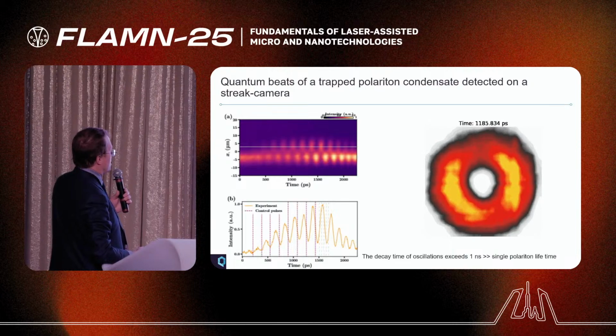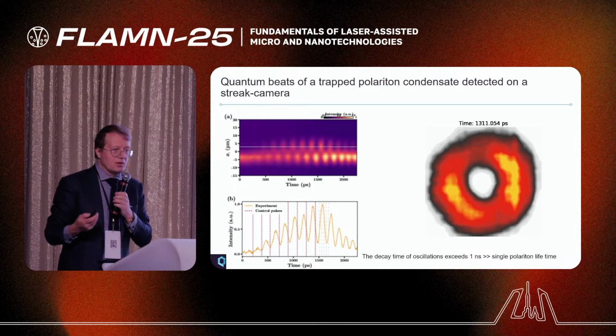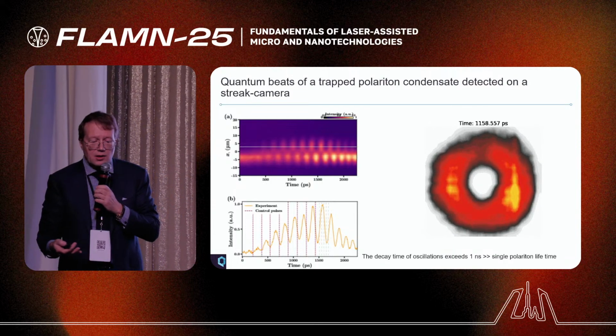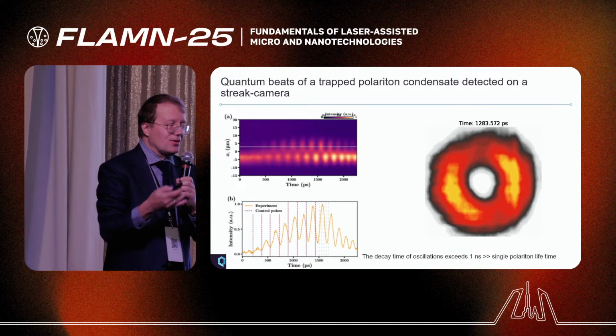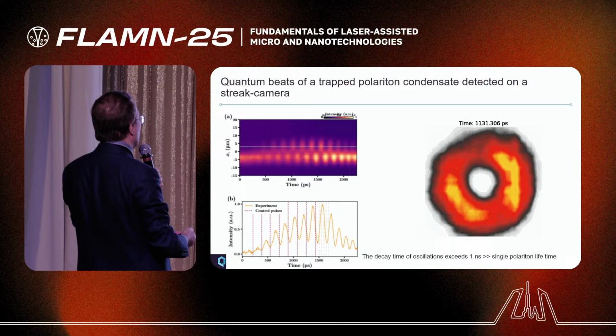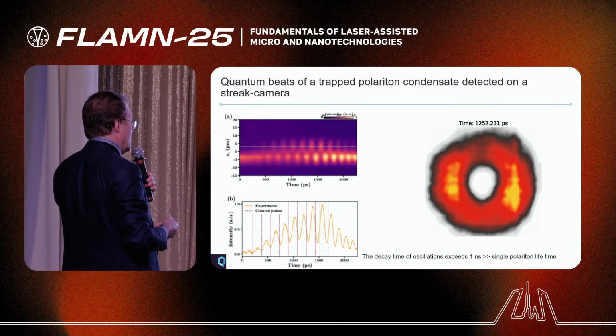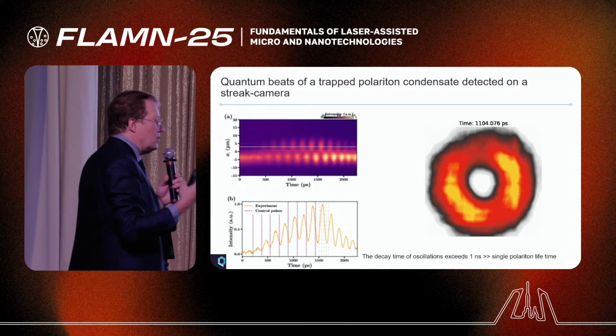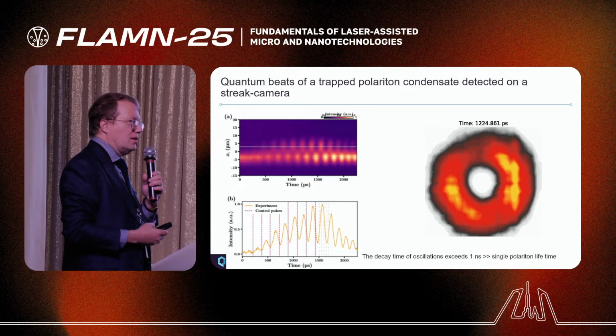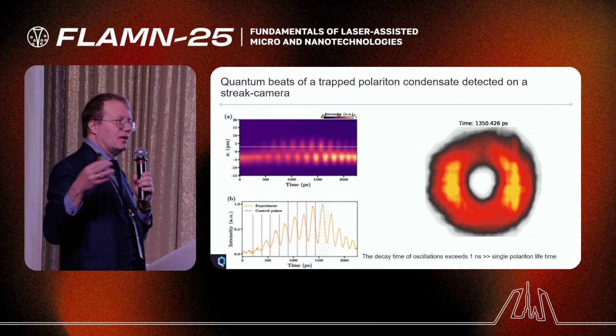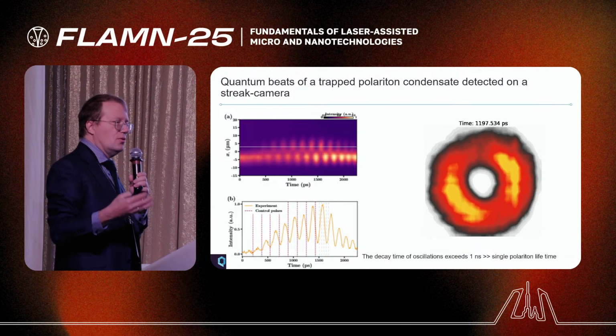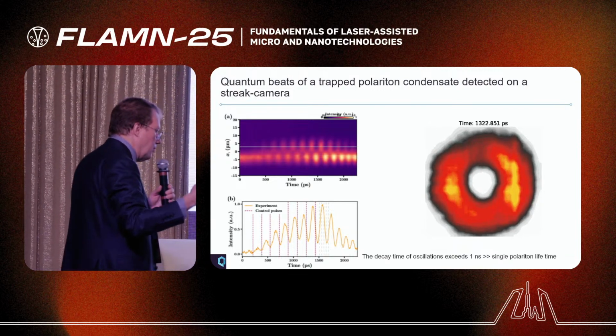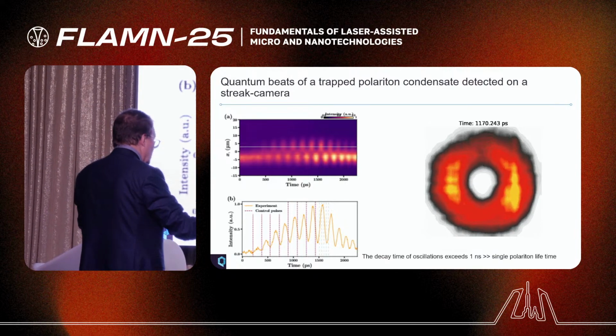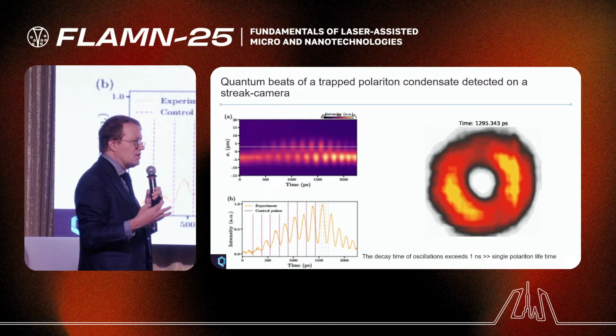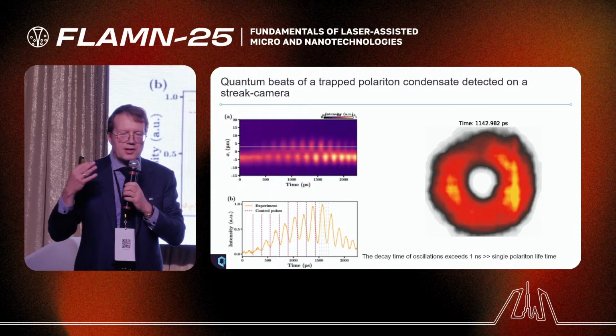These oscillations do not decay for a long time, more than 1 nanosecond. So this is much longer than the single polariton lifetime, and it gives us hope that the system is robust. Actually, Bose-Einstein condensates, as I told at the very beginning, are much more robust than individual polaritons. And qualitatively, this is because an individual polariton can just disappear. But when you have 10,000 of them, one goes out, one comes in, and the whole bunch of particles still carries on. They keep their phase, they keep their macroscopic properties. So as the Russian song says,